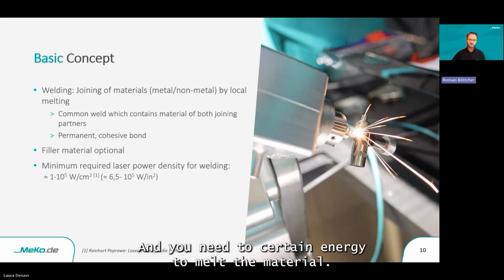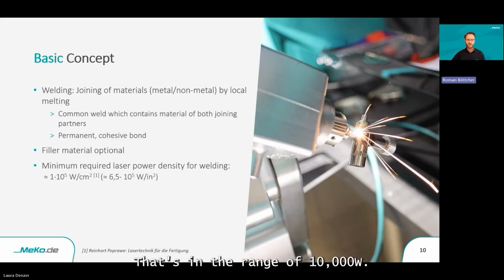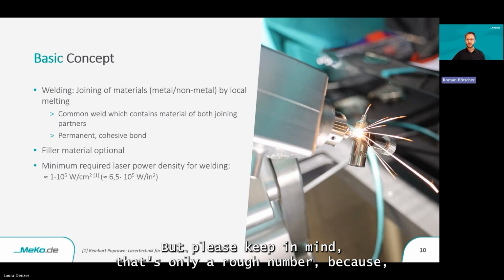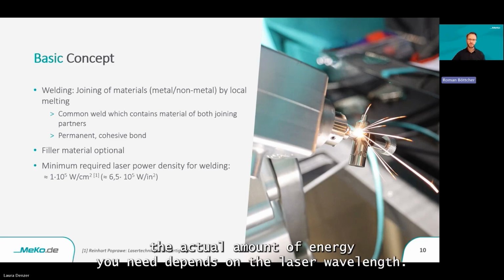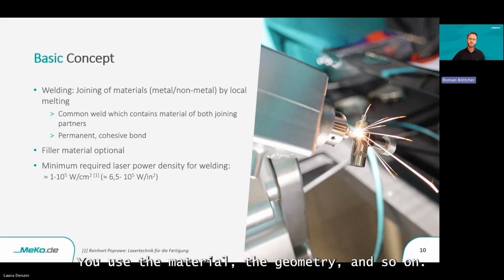You need a certain energy to melt the material. It's in the range of 100,000 watts per square centimeter or 650,000 watts per square inch. But please keep in mind that's only a rough number because the actual amount of energy you need depends on the laser wavelength you use, the material, the geometry, and